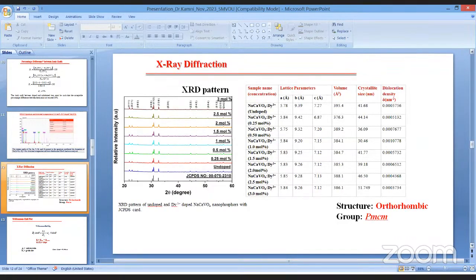So the next is the XRD diffraction pattern of undoped and dysprosium doped NaCaVO4 nanophosphor with the JCPDS card. The phase and the structural qualities of the doped matrix were examined by means of PXRD findings. Intense, clearly defined, and prominent peaks in the XRD data suggest that the phosphors are crystallized in orthorhombic phase with a space group of Pmcm, as suggested by comparison with the standard card, which is shown on the lower side. Then various parameters, lattice parameters a, b, c, volume, and crystallite size were calculated by making use of